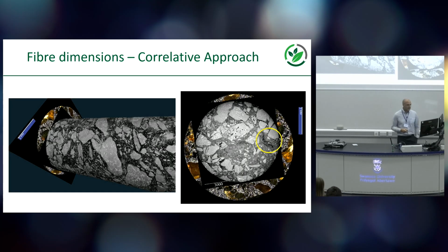So what Nick did in a very painstaking way, Nicola's over there, by the way, is correlated this to more conventional optical microscopy, okay? Not simple in terms of how we did it. So what we did is we identified a region where we had non-uniform distribution of these fibres to see if we could pick out the detail of that region. And we took the 3D volume and then correlated it to a 2D plane, cut the material in half, and then actually imaged that surface and placed it back into the 3D volume so that we could correlate an optical description of the microstructure with an X-ray description of the microstructure.